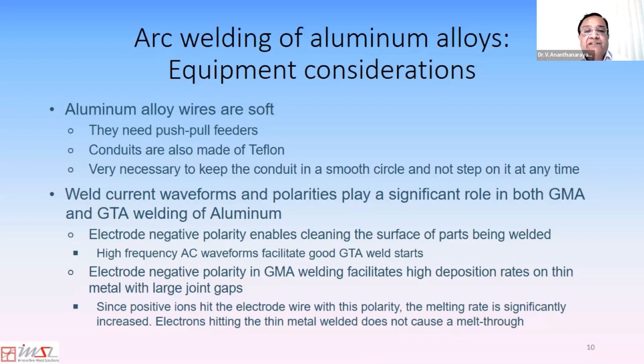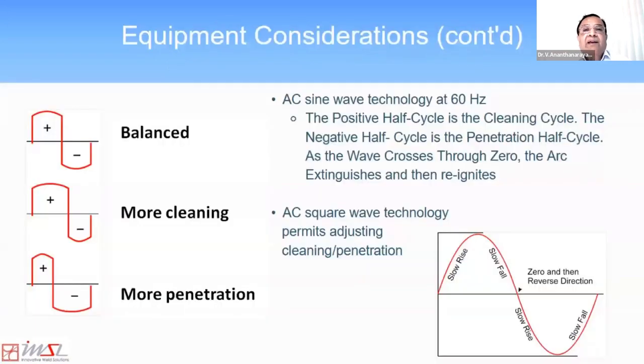So understanding the effects of these waveforms in aluminum alloy welding is very important. And if you look at TIG welding, you can have balanced AC sine wave technologies at 60 hertz here, or in India, it may be 50 hertz. The positive half cycle is cleaning, the negative half cycle is penetration. And so if you have AC square wave technology, you can have more cleaning or more penetration as your joint geometry dictates.